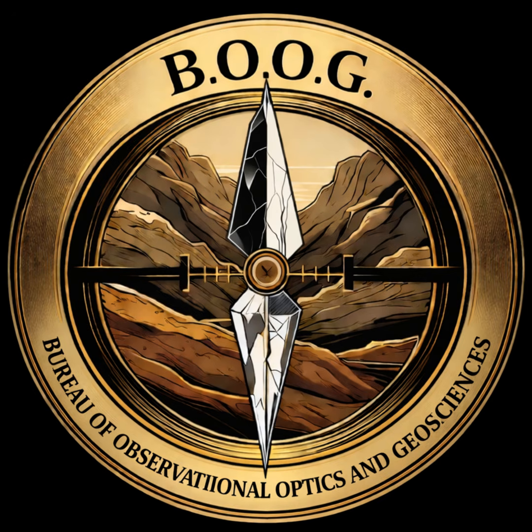But it doesn't just improve the clarity, it actively upgrades the color. That is the secondary benefit of dissolving the rutile. The titanium that was locked up within those needles is suddenly released and dispersed throughout the lattice. Oh, and we need titanium for blue. Exactly. Once liberated, this newly available titanium pairs up with existing iron ions within the stone, initiating the intervalence charge transfer, the quantum electron jump that we detailed earlier. So they basically activate the hot potato game. Yes. So through the application of extreme heat, a dull, cloudy, pale stone is transformed into a highly transparent, intensely saturated blue gem. It is essentially putting the geological formation process on fast forward, giving the stone the heat it lacked deep underground.